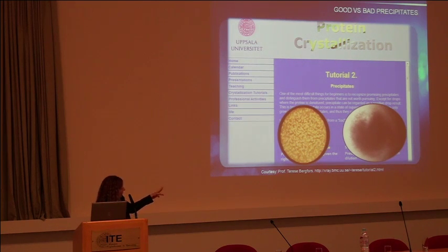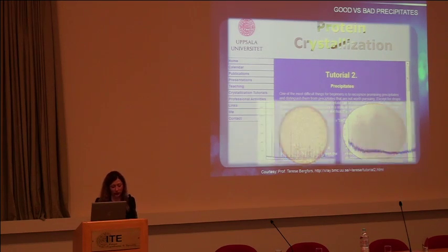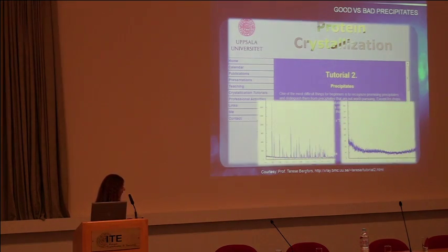And if we put these two samples in front of an X-ray beam, this is what you will see. In the case of the amorphous, we get only a background, and this is a sample that you can study with small angle X-ray scattering, for example, but no diffraction. The microcrystalline sample gives data which have diffraction lines, and this is exactly the data set that we require for further structural analysis.